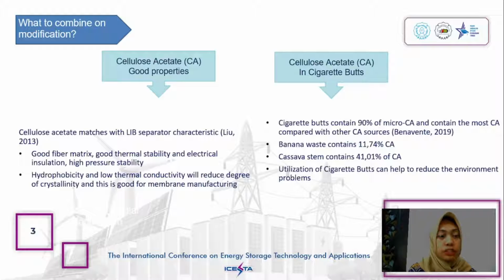So what to combine in this modification? We choose to use cellulose acetate, or CA, because its good properties match with LIB separator characteristics, such as good fiber matrix, good thermal stability and electrical insulation, and high pressure stability. Its hydrophobicity and low thermal conductivity will reduce the degree of crystallinity, and this is good for membrane manufacturing. As the source of the cellulose acetate, we choose to use cigarette butts. Why? Because cigarette butts contain the most cellulose acetate compared with any other CA sources such as banana waste and cassava stem. And this utilization of cigarette butts can help to reduce environmental problems.